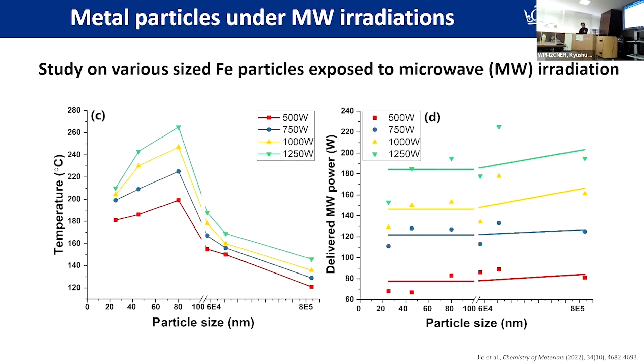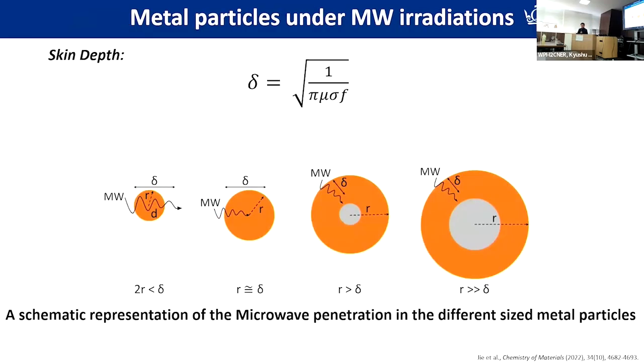The best heating performance is observed at 60 to 80 nanometer size. And why is this? This is because of the skin depth of the microwave. The skin depth of the iron material is about 48 nanometers, or perhaps 42, if I'm wrong. And the skin depth describes how the microwave penetrates through the material, and the power decreases to 1 over e.